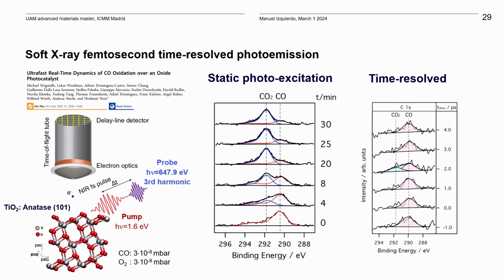In this case, what they studied was the oxidation of CO, using 800 nanometers again. They went into the soft X-ray regime, the third harmonic of FLASH, and put CO and O2 at 3 × 10⁻⁸ millibar in the system. What happens as a function of time? If you put CO and O2 and you don't put any light, nothing happens. So then you can stay there forever.